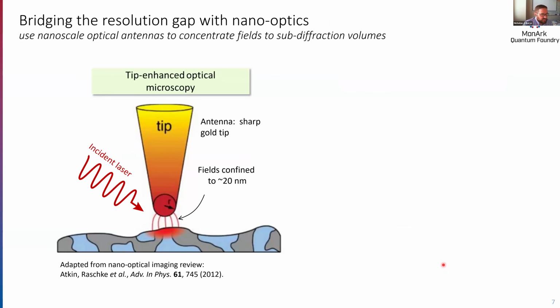And so the good news is that there's a way to bridge this resolution gap, and this is with nano-optical imaging and spectroscopy. This is a schematic of tip-enhanced optical microscopy. Rather than using just a normal optical microscope, this technique involves bringing a sharp gold tip, usually a metal-plated AFM probe, in very close proximity to the sample. And then this tip-sample junction is illuminated with an incident laser.